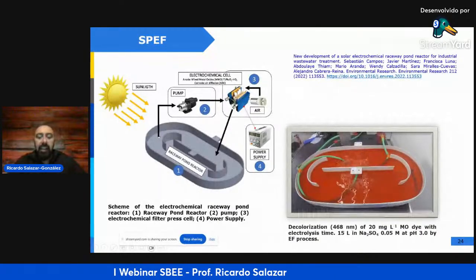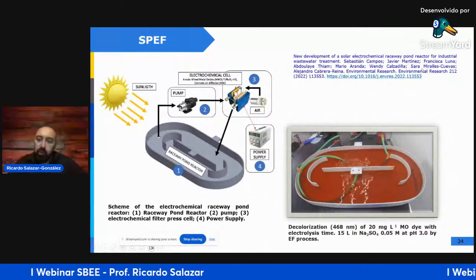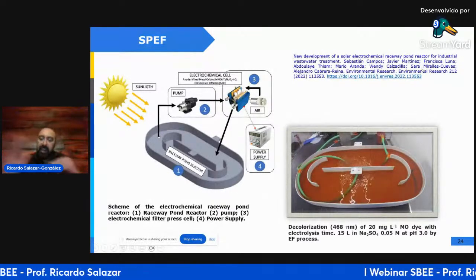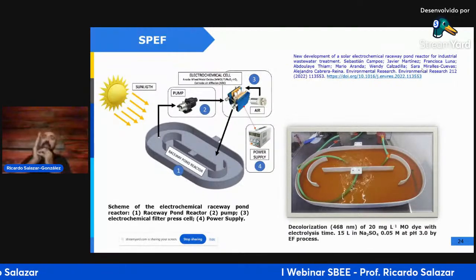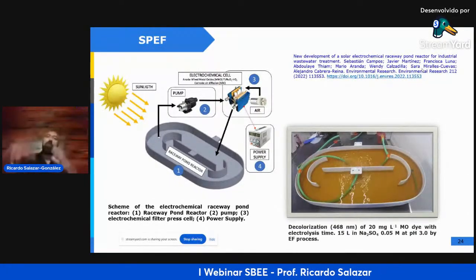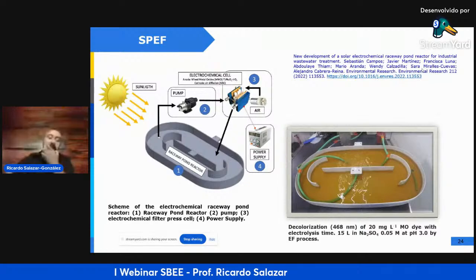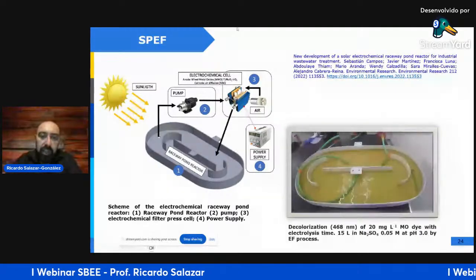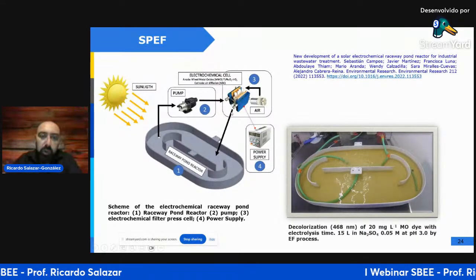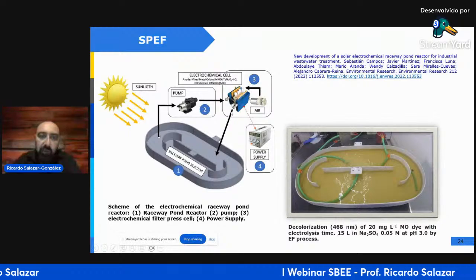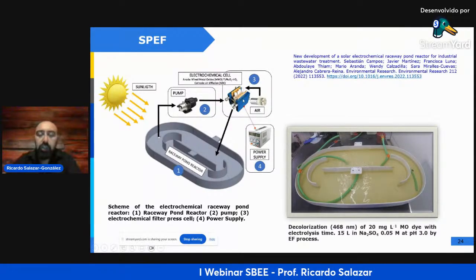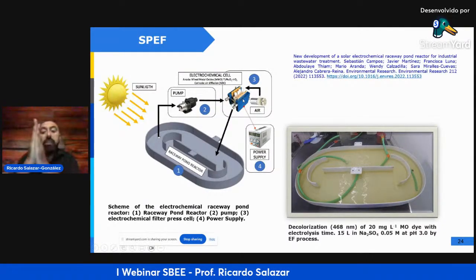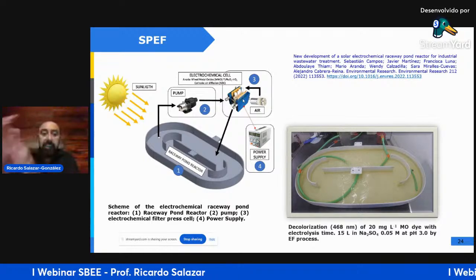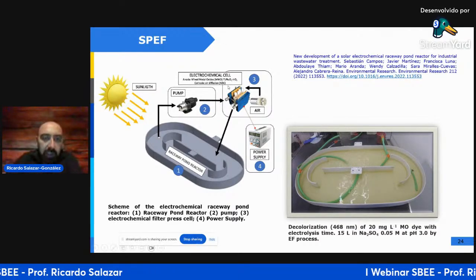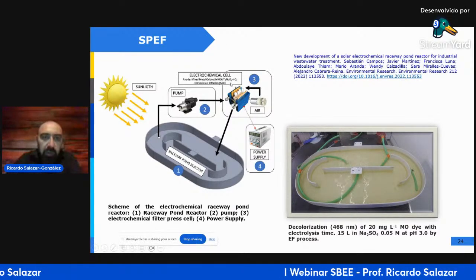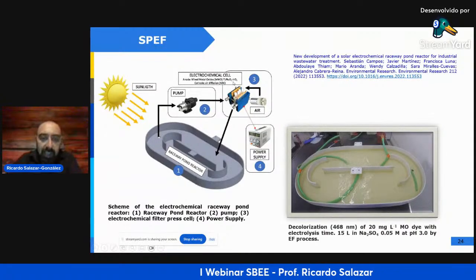Here we use an open photoreactor to produce direct interaction between the solution and the sun radiation. We produce hydrogen peroxide in an electrochemical filter press cell containing a carbonaceous cathode with graphite and an anode containing ruthenium and iridium oxide.